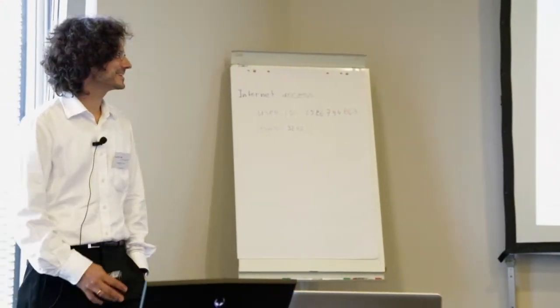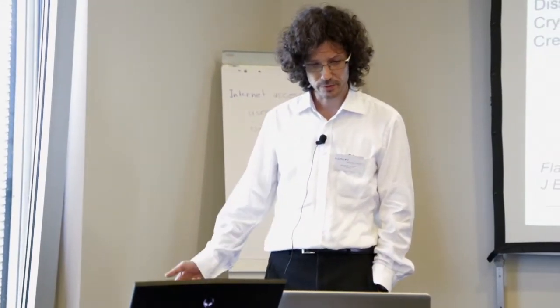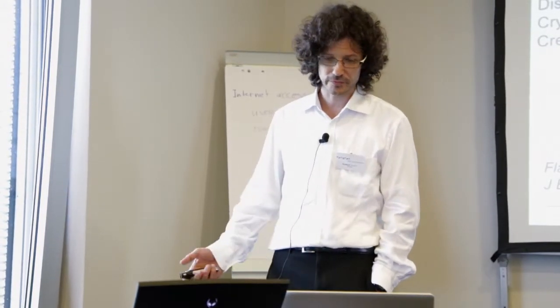So, more seriously, let's talk about what one can do with chemical admixtures and advanced solutions. These are substances that work when added in small amounts, and the reason why they are so effective is that they act at interfaces. So think about concrete with solid, liquid, vapor phases at different stages of its life. You have solid-liquid interfaces that control processes of agglomeration, adsorption, dispersion, that control dissolution, nucleation, and growth, crystallization pressure, or creep. Liquid-vapor interfaces controlling capillary pressure, surface tension, air entrainment, solid-vapor interfaces for dry dispersion or hydration pressure, for example. And you can fill in the diagram, avoiding, of course, the vapor-vapor interface, and not forgetting solid-liquid interfaces, which are important for corrosion.